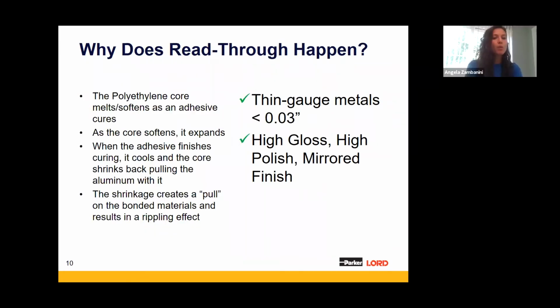So now let's look at why read-through occurs. Well, read-through occurs because, especially on ACM, which stands for aluminum composite material, it's essentially two thin sheets of aluminum that sandwich a polyethylene core. Now, when an adhesive cures, sometimes it gives off heat, and sometimes that heat is so great that it melts that polyethylene core. And as the core softens, it expands. And then the adhesive, once it's finished curing, it then cools and the core shrinks back, pulling the aluminum with it.